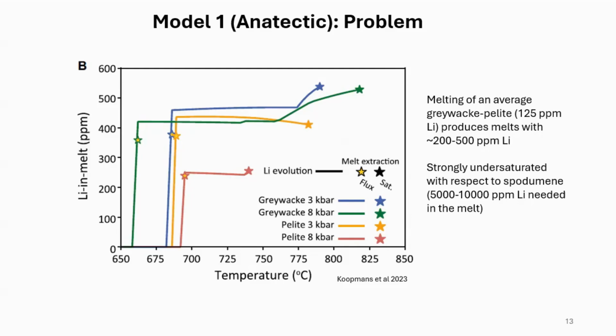So if we take a metasedimentary rock, either a graywacke or a pelite with about 125 ppm, that's global average, not a special rock. It doesn't have to be a rock that had started out with 3,000 ppm lithium in it, and that's what we melted. No, this is just a graywacke or a pelite with 125 ppm global average lithium. If we melt that, depending on the temperature, this is where the muscovite comes in first, and then we start to melt out the biotite, and the lithium concentration in the melt increases as biotite is progressively melted out of that rock.